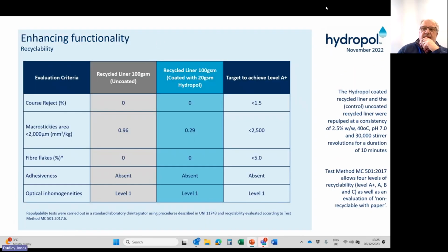If you look at the actual numbers of that, we took a 100 GSM recycled liner. We coated it with Hydropol. We got 0 coarse rejects, very low micro stickies, no fiber flakes, adhesiveness was absent, and when it came to optical, we got a level 1. So it was a good result in terms of its recyclability credentials.